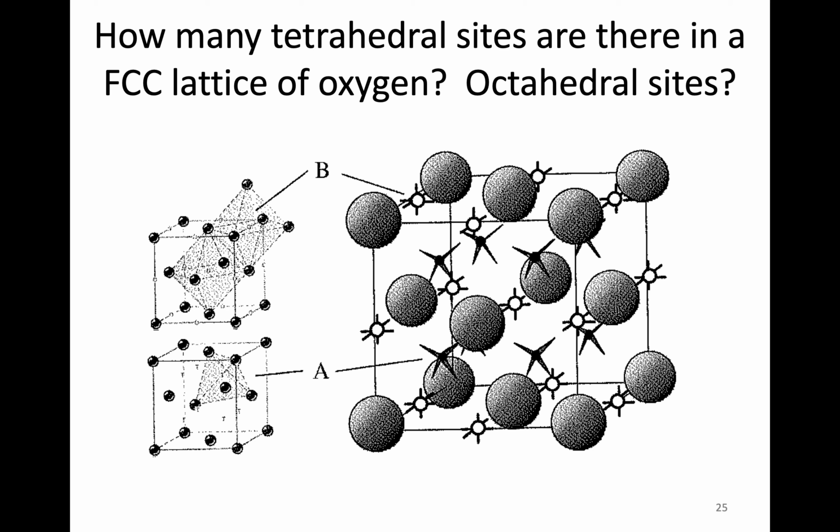This is what we think of. We think of these ionic ceramics as having an anion packing of one of the close packed structures, so either FCC or HCP. And then we take the cations of that ceramic and fill them into some combination of the interstitial sites, tetrahedral or octahedral.